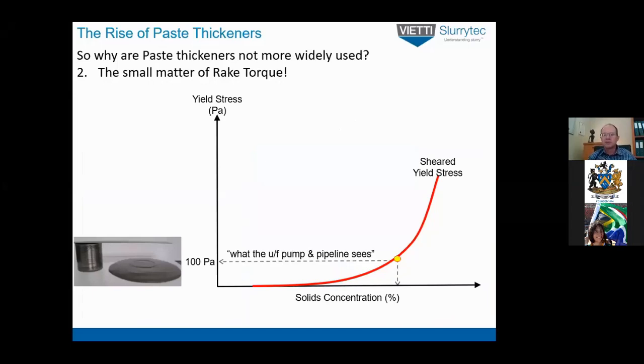In most definitions, when you see a yield stress curve, it's the sheared yield stress curve. Because the pump and pipeline designers and the geotechnical engineers deal with material that's gone through a pump and been sheared all along the pipeline, and it ends up at the tailings dam in a sheared state. So they're interested in the sheared yield stress of the material, while the thickener guys are more interested in the unsheared yield stress, because that's what the rake and the rake gear drive sees.